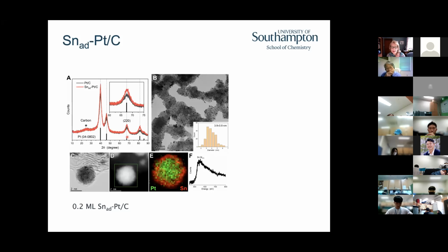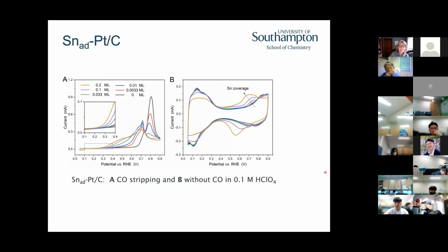So what do they look like? Here's the tin that's decorating those platinum particles. You can see that we have no alloy, as evidenced by the X-ray diffraction. The particle size distribution stays nice and small. From the TEM and the EELS mapping, we can see that the tin is really sitting on the surface of the particles. That's lovely. That's with 0.2 monolayers.